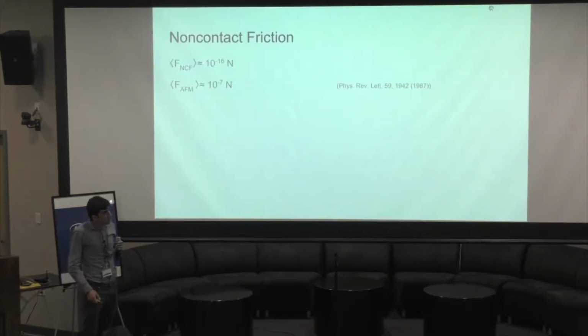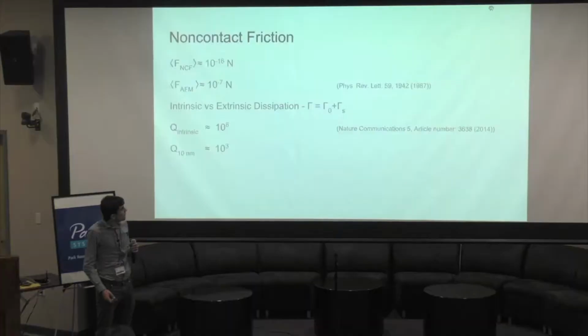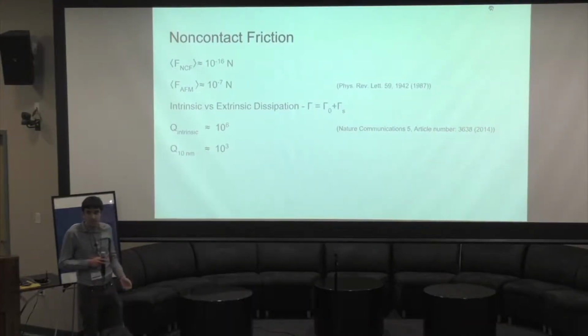So this is a very, very small force. The kind of friction that's typical in AFM measurements, for example, dragging an atomically sharp tungsten tip over a graphite surface, is on the order of 10 to the minus 7 newtons. The kind of forces that are relevant in non-contact friction are on the order of 10 to the minus 16 newtons. But it turns out that they have a pretty substantial effect.